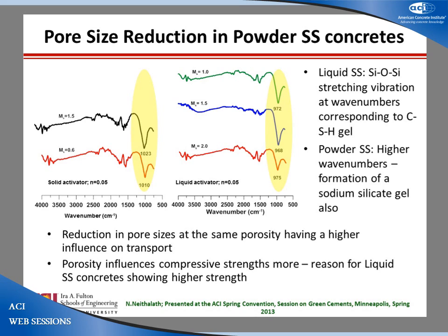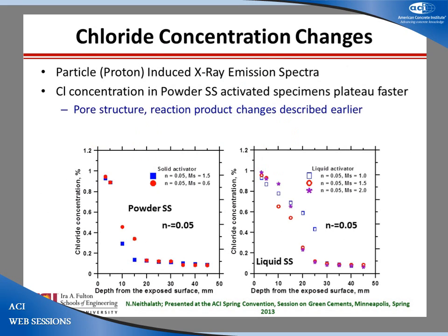And therefore, the pore size is also lower. And therefore, the powdered sodium silicate activated mixes have reduced pore sizes. So they have lower strength. Strength is much more dependent on porosity, so they have all lower strengths, but they can give you better transport properties because of their lower pore sizes. So one thing to look for, even if it's not completely dissociated, one advantage of using a powder activated sodium silicate. Chloride concentration changes over the depth using particle-induced X-ray emission spectra.